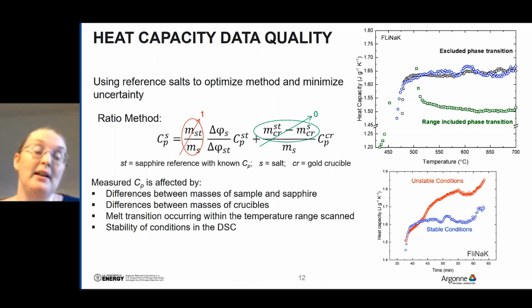We have noticed that the measured Cp is affected by a variety of things, some of which are listed here. Differences between the masses of the sample and sapphire need to be minimized so that first term goes as close to 1 as possible. And then the differences between the masses of the crucibles need to be minimized so that the effect of the crucible material is minimized as well.